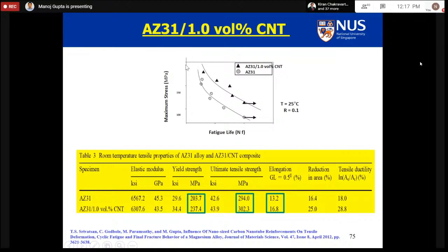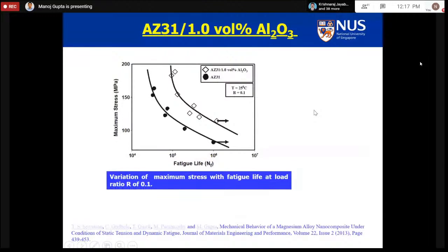And if you look at this graph here, stress versus number of cycles to failure, for a given stress, the number of cycles to failure for a composite is always higher. Similar results were obtained for Al2O3 reinforcement. For a given stress level, the number of cycles to failure is higher.